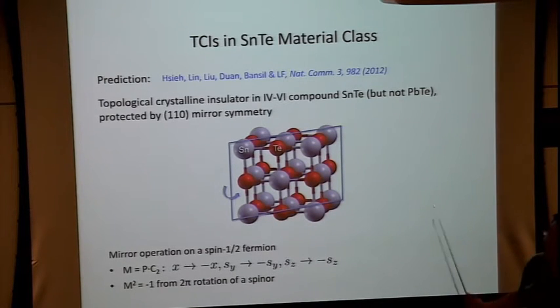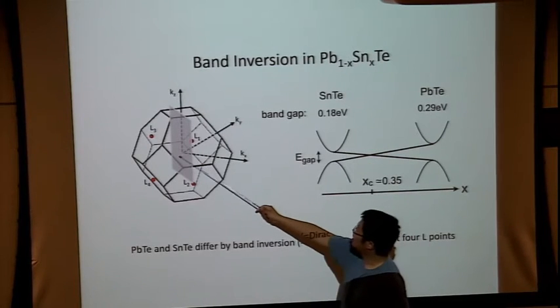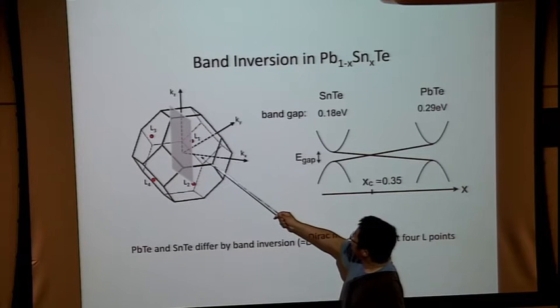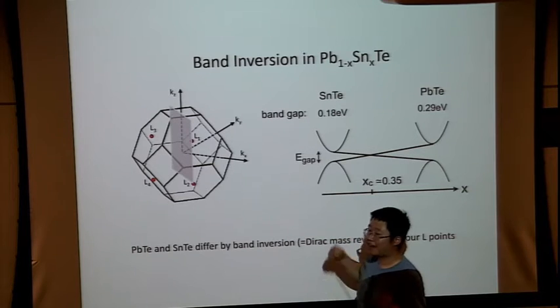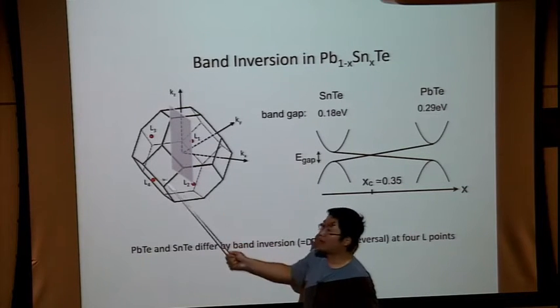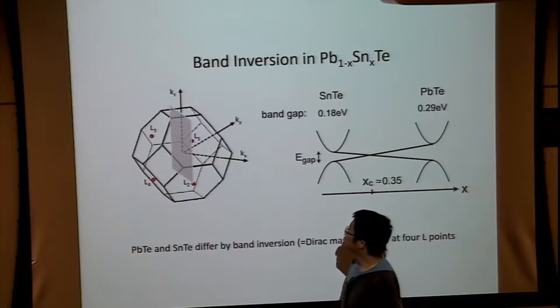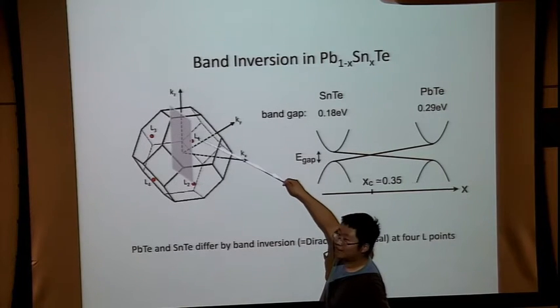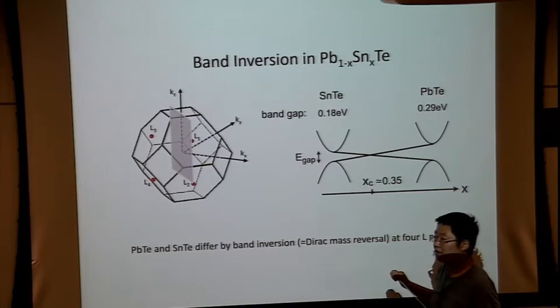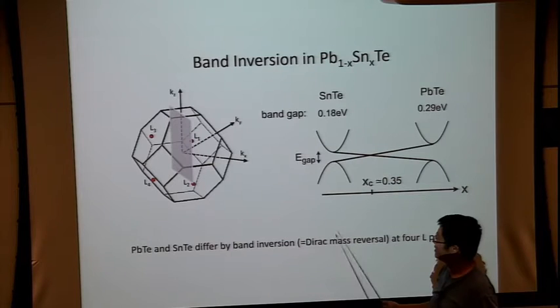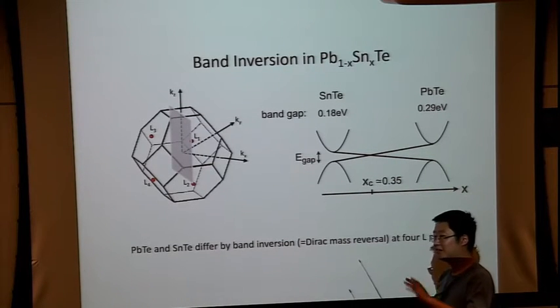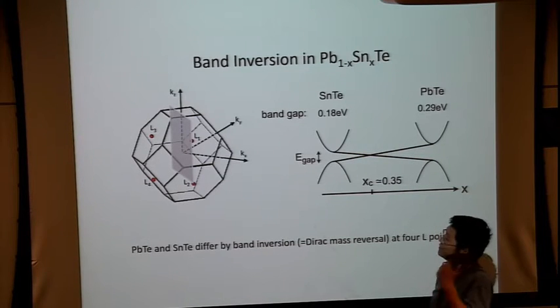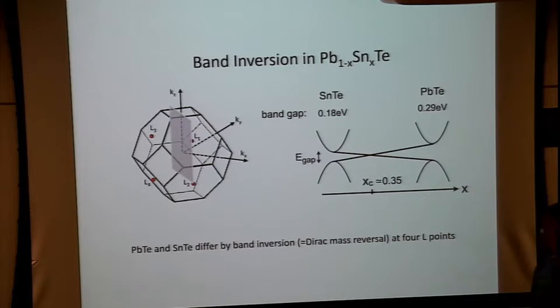So let me now focus on a particular reflection symmetry. For a particular reflection symmetry, there are two L points that lie on that plane. L1 and L2 lie on this plane, while L3 and L4 lie on another reflection plane. Given multiple mirror symmetries, absolutely. In this particular compound, all these reflection symmetries are related by rotation symmetry, so the mirror numbers on these planes are all equivalent. But for simplicity, let me just talk about one mirror plane, and imagine that all other symmetries are gone, with only one reflection symmetry left. Then this band inversion between lead telluride and tin telluride should lead to one topological phase, either lead or tin telluride.